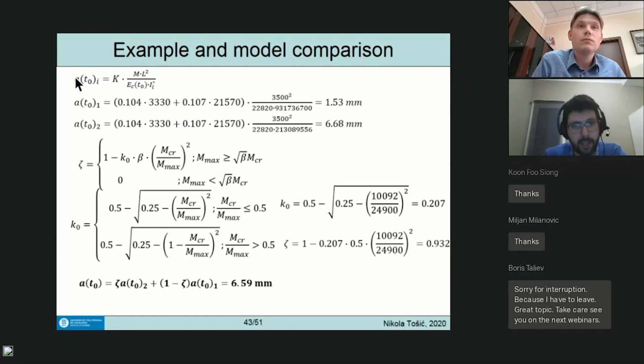From load, you calculate deflection as K, a factor that depends on the statical system and loading, times M L squared over the stiffness, at modulus T0. K is 0.104 for uniformly distributed load, multiplying the moment from self-weight, and 0.107 for loads from two forces in the thirds, for 4-point bending, multiplying that moment, times L squared over the stiffness.